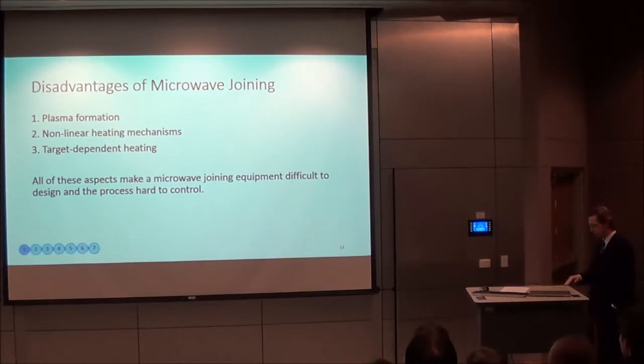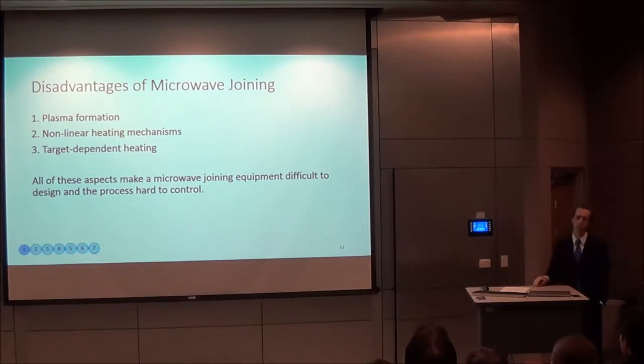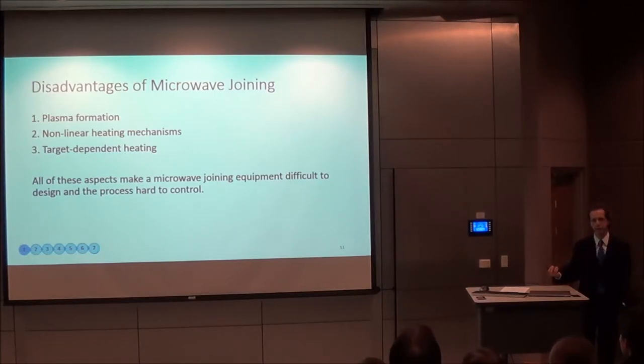Also, microwave heating is fundamentally target dependent, and so based on the properties of the material and the size and shape of the target, the heating will be very different because the degree of coupling to the material will be different.